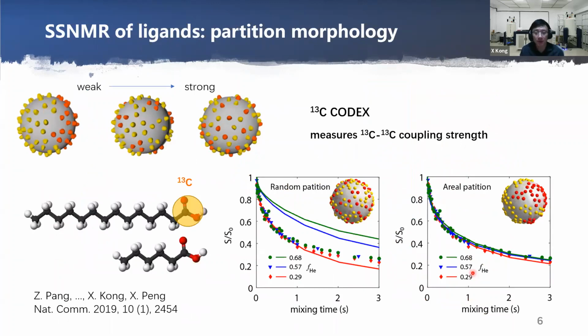In another study, we tried to solve the surface morphology of mixed ligands on nanocrystals. This study utilized the CODEX pulse sequence to decode the homonuclear coupling between the C13 labeled ligands. For different partition morphologies, the overall coupling strengths of the C13 can vary notably, and therefore we can identify the characteristics of surface morphology, and we show that the areal partition is evident for spherical nanocrystals.